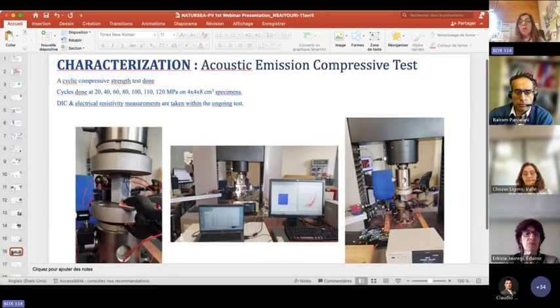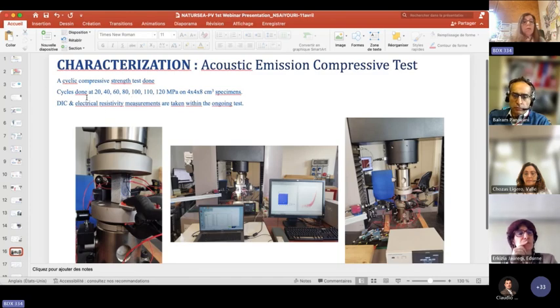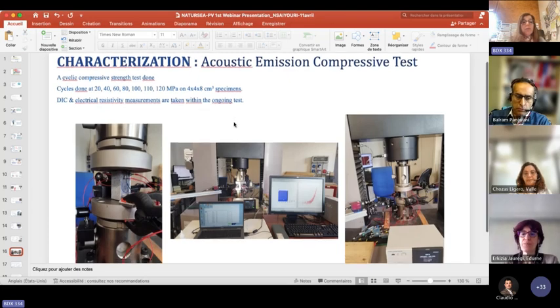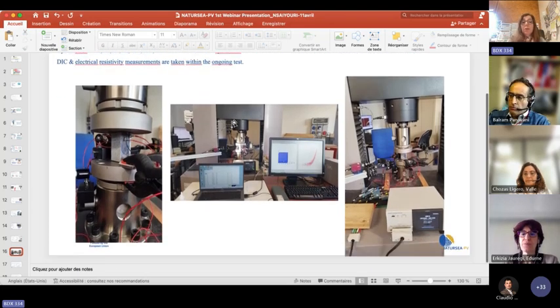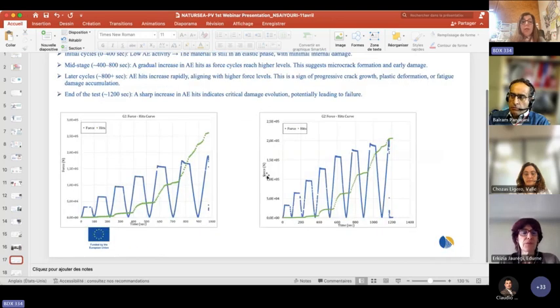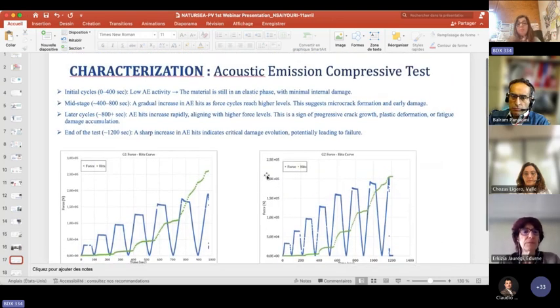Acoustic emission was also done with compressive tests. We have the device here, so we have the gauge here, as you can see, and we applied a cyclic compressive strength test on specimens of 4x4x8 cm³, and cycles are from 20 to 120 megapascal, and electrical resistivity measurements are taken within the ongoing tests. We can show some results.